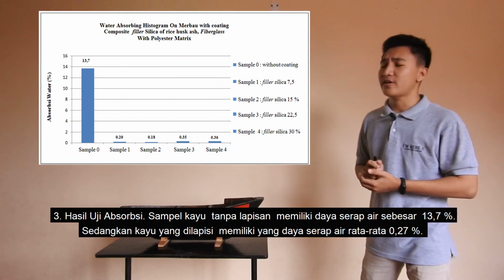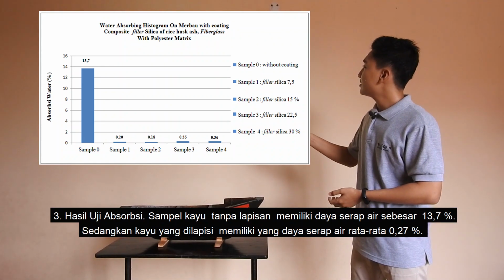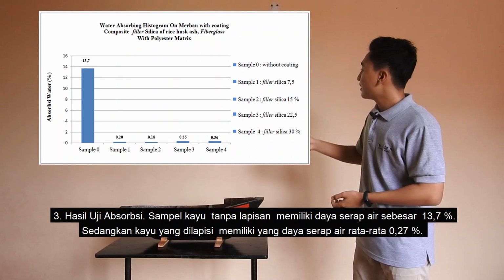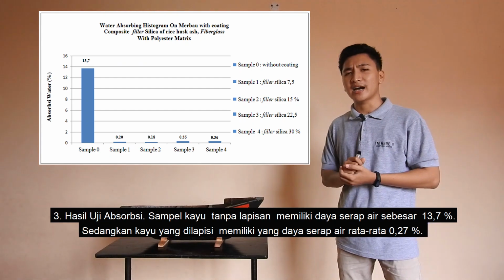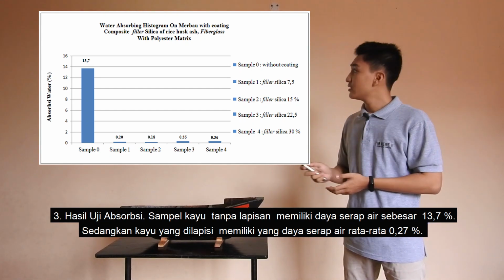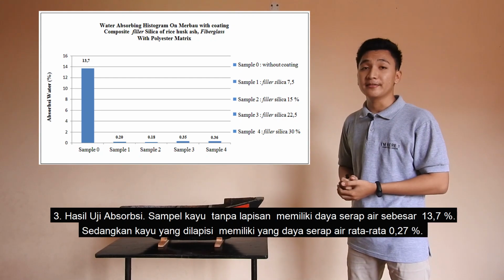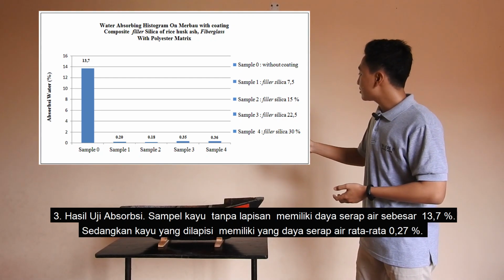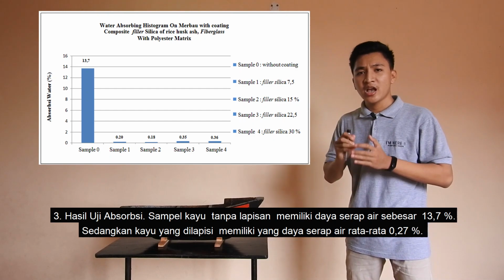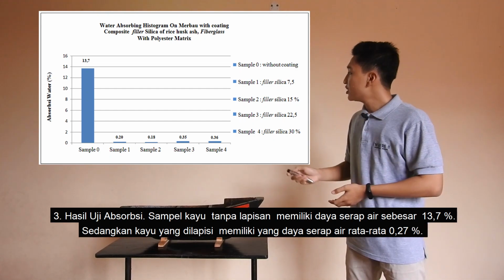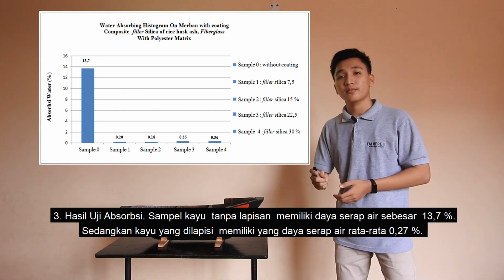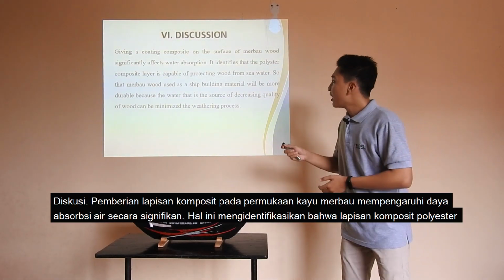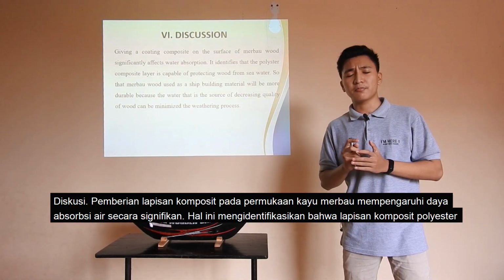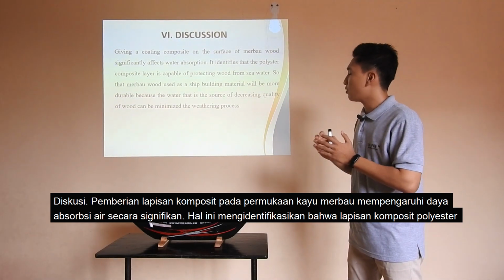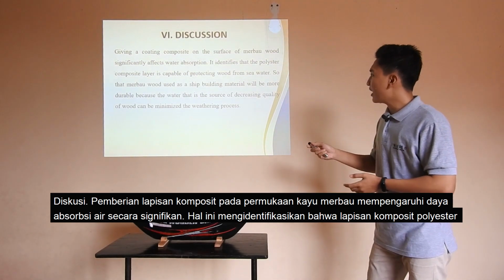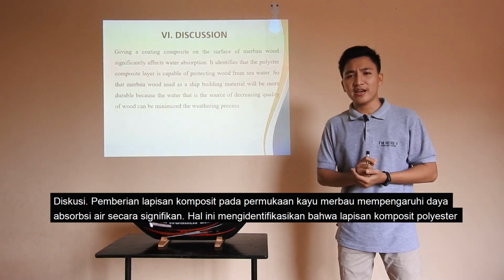And the third, result of absorption test. We can see from the histogram that sample 0 without silica filler has water absorption capacity 13.7%, while the samples given silica filler have water absorption of 0.27%. Discussion. Giving a composite coating on the surface of merbau would significantly affect water absorption, so that polyester composite layers are capable of protecting wood from seawater,